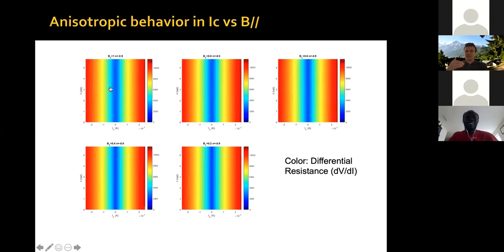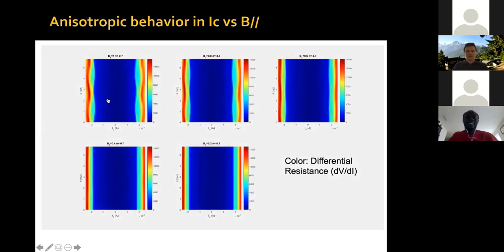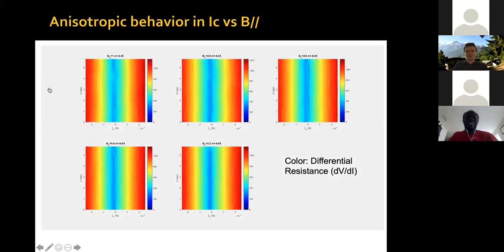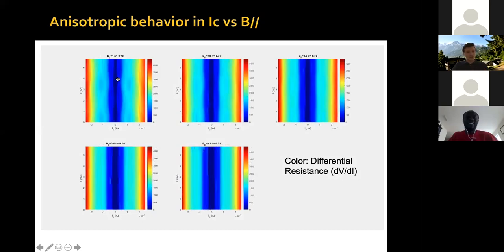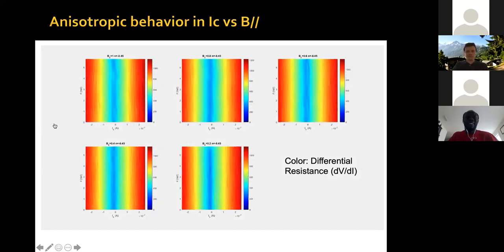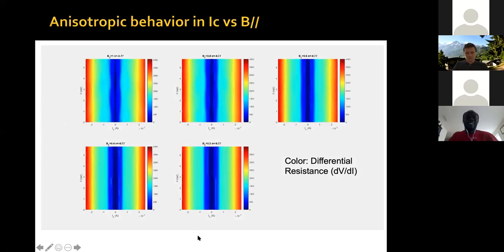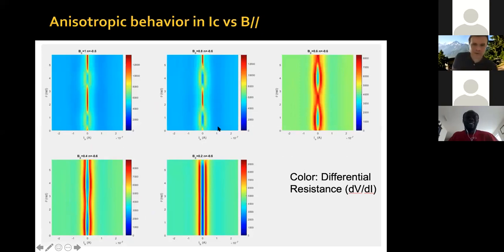And the video that I'm going to run goes through different densities. So again, we have so many knobs in this system that we have to take these multi-dimensional space plots and show them as videos. Let me just run this, okay? So as you can see, as we vary the density for certain regions, you have these anisotropic responses. Let me just run it again. Now you see there anisotropic responses. Let me stop it and take a snapshot at one particular density, okay? You can see here that for this particular density and at different parallel magnetic fields, for example at 0.8 Tesla parallel magnetic field, as a function of rotation angle, for some angles the system is superconducting, and for some angles the system is actually insulating.